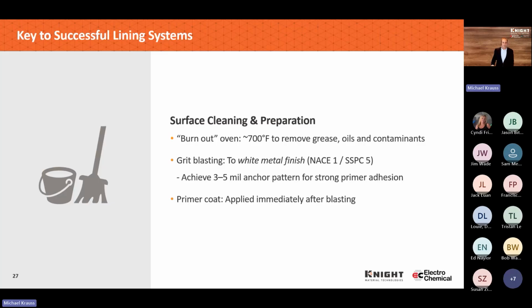In terms of surface preparation, in order, again, to be able to get good bonding, you need to make sure any greases, oil, or contaminants are removed prior to lining. Grit blasting to a white metal finish and putting on a really strong 3 to 5 mil anchor profile is critical for getting an adhesive system to bond to it. And then getting a primer coat applied to it immediately after blasting so that no rouging or rust starts setting in, which will limit the capability of bonding, is really critical and important.